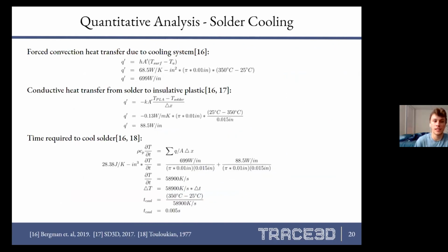So we began the quantitative analysis for our system by first looking at a thermodynamic approach. We modeled the two most important modes of heat transfer, those being the forced convection due to the fans in our cooling system, as well as the conductive heat transfer due to deposition of hot solder. We found that the time required to cool a unit length of solder was 1/200th of a second.